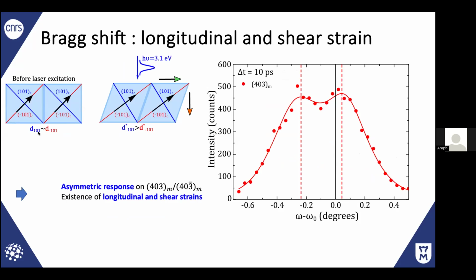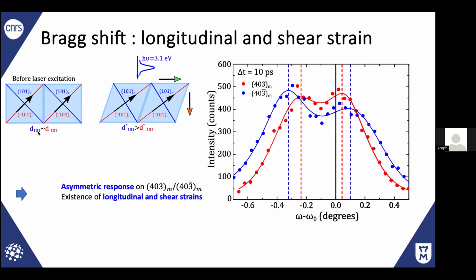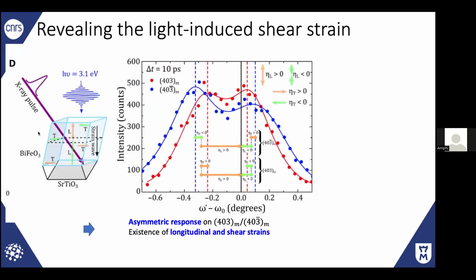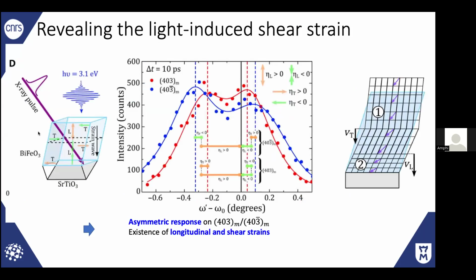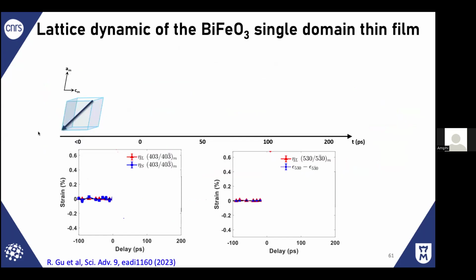What is interesting is that we did it for that Bragg peak, but that one is not equivalent. Why? It's a bit technical, but if you combine both measurements, the difference between two Bragg peaks is just due to the presence of the shear strain. So finally, by making two measurements, you can reconstruct the longitudinal one and the shear one. So this is, finally, the picture, I can go directly to that one.